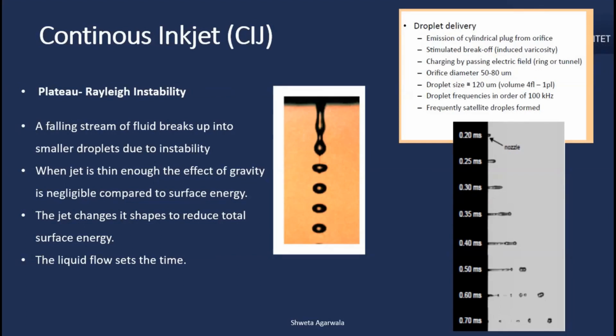part of inks. And again, if you were to look at it in a very realistic, theoretical way, then one scan or one movement of a printhead from X to Y direction should be enough, right? I have a few deposited drops in a continuous line, and that should be good enough. In reality, these drops are so small, and they even coalesce together and shrink in size after sintering, that one print pass, especially in inkjet printing, is not enough.